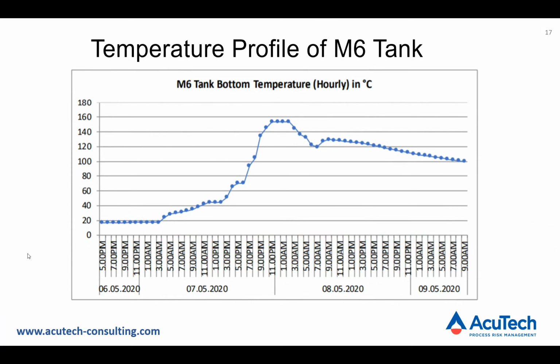The rate of increase of the temperature slightly reduced between 5 a.m. to 9 a.m. and thereafter again started increasing, even though the tank cooling measures were being undertaken by the site using the dilute system. From 3 p.m., there was a further increase in the rate, and finally the temperature peaked around 154 degrees centigrade. That was recorded around 10 p.m., which was equivalent to 1.25 atmosphere pressure, and that continued the release of styrene vapors in the uncontrolled branch.